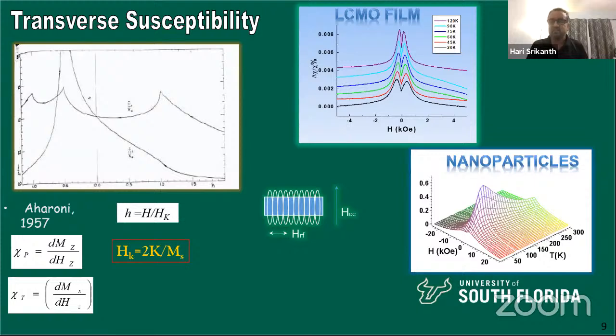So here's, for example, 20 nanometer nanoparticles of maghemite, Fe2O3, all the way from high temperature to low temperature. You can see that that's the blocking temperature right here. So you have a superparamagnetic response at high temperature, and then this blocking here. And you can also see how these peaks, the anisotropy fields, evolve. Since anisotropy field is one of the most fundamental and important properties of magnets, right? So we have a very unique and quick way of rapidly screening different kinds of nanoparticles and looking at the switching and anisotropy fields. So that's the importance of this technique.